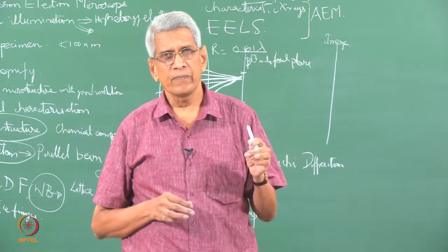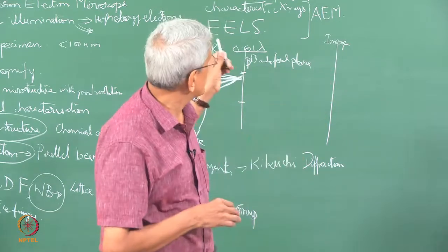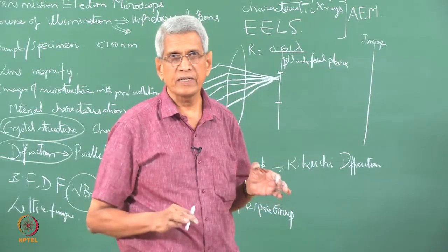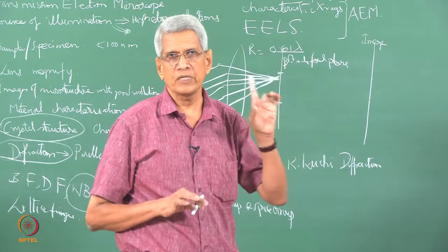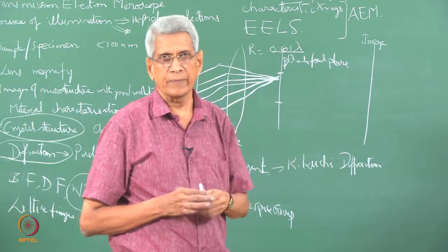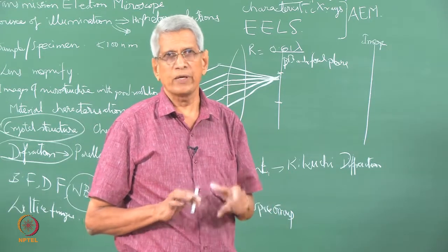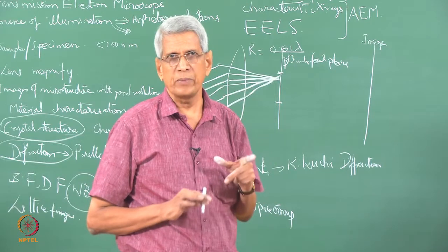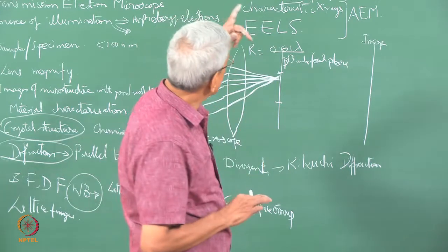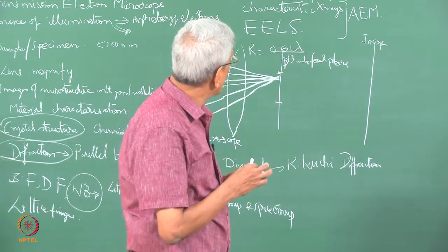As we have studied earlier, the reciprocal lattice also exhibits the same symmetry of the crystal, and similarly the diffraction pattern. So, if you look at the diffraction pattern taken in different directions, and you find that only one two-fold symmetry is present along a specific direction, then the crystal has to be a monoclinic structure. On the contrary, if along three perpendicular directions we get a two-fold symmetry, but the lattice parameters are not the same in any of these directions, then the crystal structure will turn out to be orthorhombic.